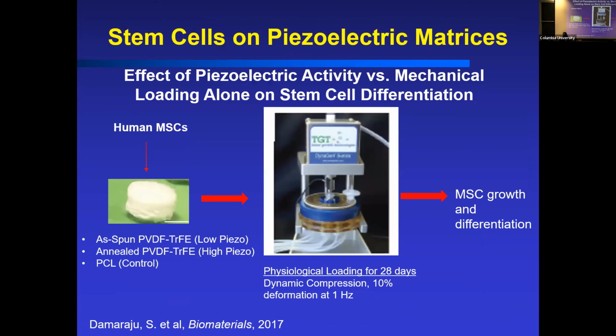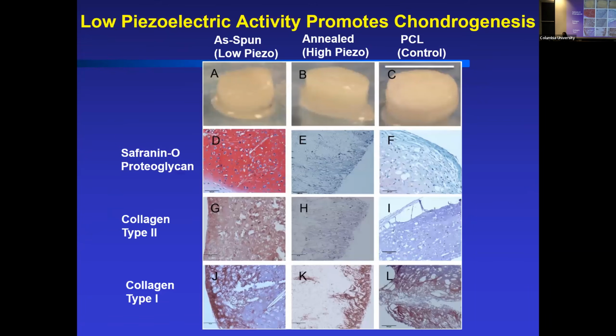And so this is great. We can look at this now to see how does it affect our stem cells? Can we drive maybe chondrogenesis or even bone differentiation? So we use this bioreactor system. And here we were able to apply a physiological load to these materials, dynamic compression at about 1 hertz frequency and about 10% deformation. And we looked at either as-spun, what we call a low piezo, or a high piezo annealed version. And we compared it to our standard polycaprolactone control material.